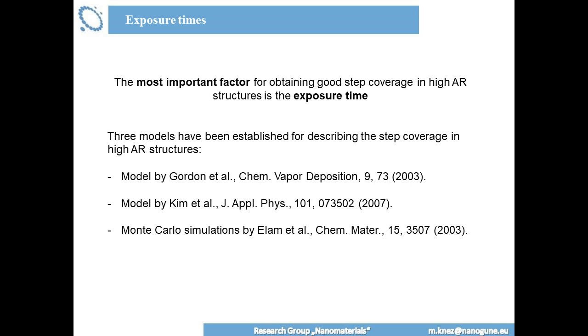Many people think, okay, I have my pore, so the deeper the pore, the longer it needs to expose, so the longer I need to give the time for the precursor, and this is correct. But what is the extension of the time you need to give the precursor? You typically tend to think it's linear, but it's not. There were 3 models set up for that purpose. So one was by Gordon and by Kim, and also a Monte Carlo simulation by Jeff Elam. I think there are some more models around, but these are basically enough to give you an idea of what the essential claim out of those is, in terms of time you need for the process.